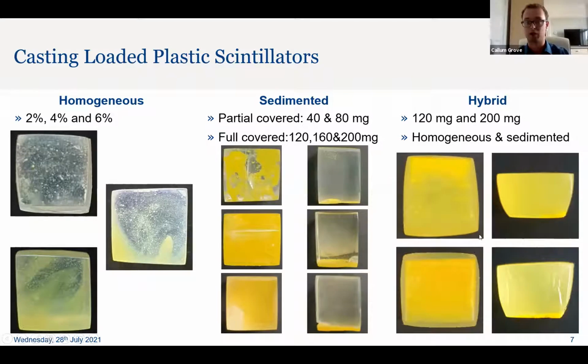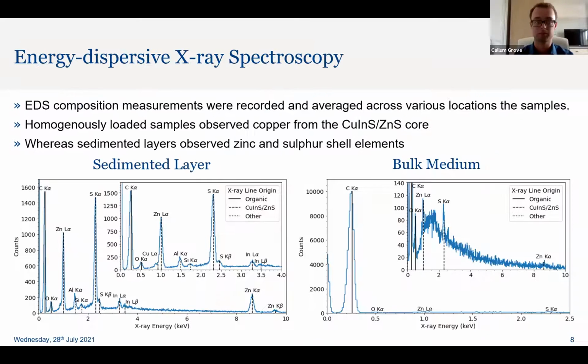And then we went for a hybrid approach where, for slightly older resin and therefore thicker resin to start with, so it wouldn't sediment as much as it had occurred here, we'd have a sedimented layer and a homogeneously dispersed region in the bulk crystal. And so they're the three batches that we'll be discussing: homogeneous, sedimented, and hybrid, so between the two.